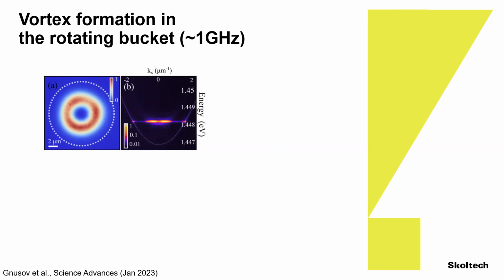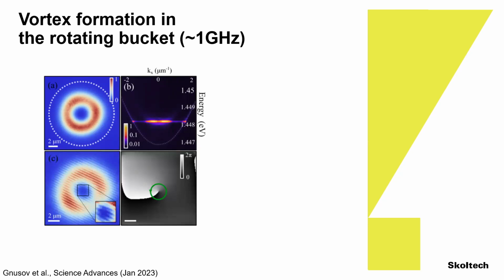But of course, that could be anything. I need to measure the phase. If I want to say that I have a quantum vortex, I need to measure the phase. So we do interferometry of the emission, and when we extract the phase, we see clearly that the phase goes around between 0 and 2 pi. So I have a flow of particles that go around this ring, and when they close the loop, the phase goes from 0 to 2 pi. So I have a quantum vortex, which is now created when I rotate the bucket of the condensate.